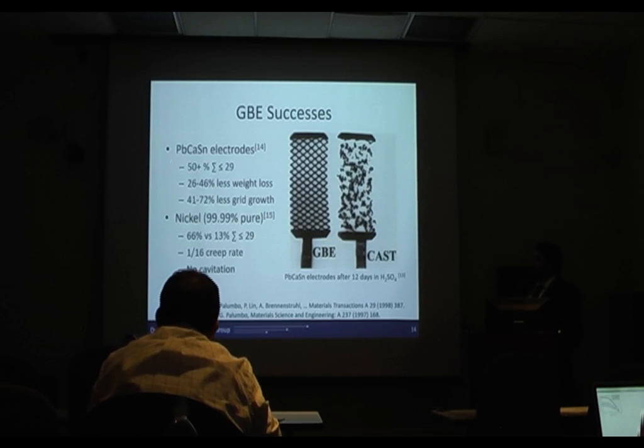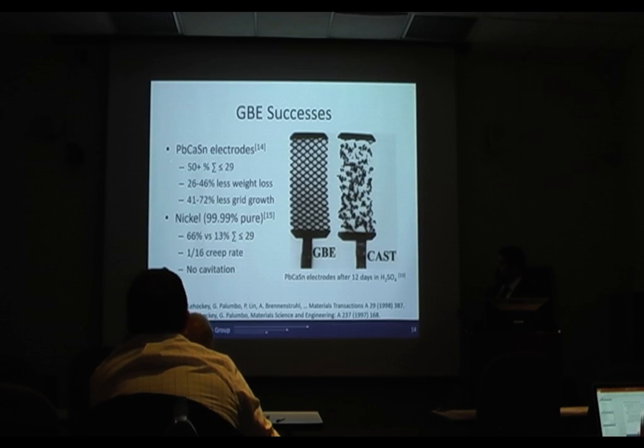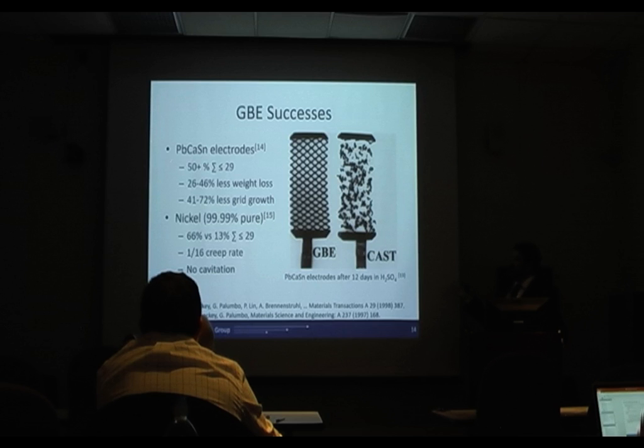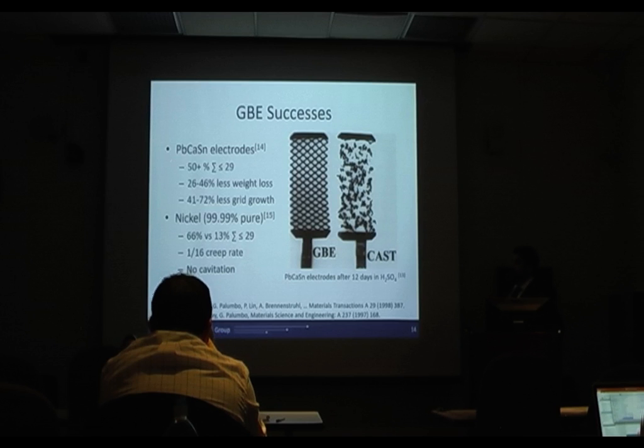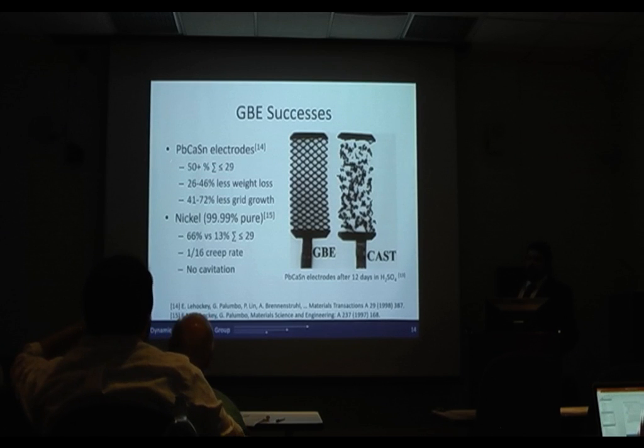On the right are shown lead acid battery electrodes, and they put in over 50% CSLs and were able to significantly reduce both the weight loss and the grid growth. And then in another study in pure nickel, they were looking at the creep rate. They went from 13% to 66% CSLs and now had 1/16 of the creep rate and completely eliminated cavitation.